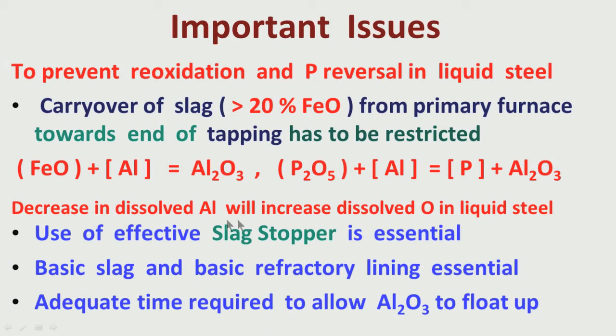Now what happens because of these reactions with FeO and P2O5? The dissolved aluminum, whatever was present, will come down due to reoxidation. And in the process, what is going to happen? Because the product of the weight percent of dissolved aluminum and the weight percent of dissolved oxygen is constant, as I have told you earlier, if the dissolved aluminum comes down, dissolved oxygen in liquid steel will increase. This is going to affect the cleanliness of the steel. So reoxidation will take place, phosphorus reversal will take place, that means phosphorus also will increase in steel, and because soluble aluminum is coming down, dissolved oxygen in liquid steel will increase. So these are creating a cleanliness problem.